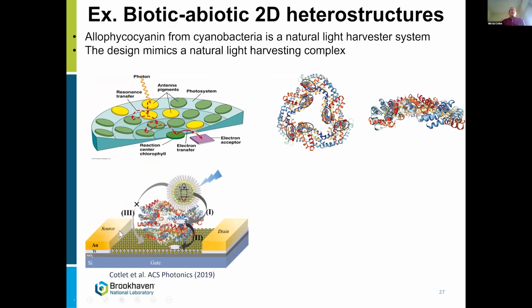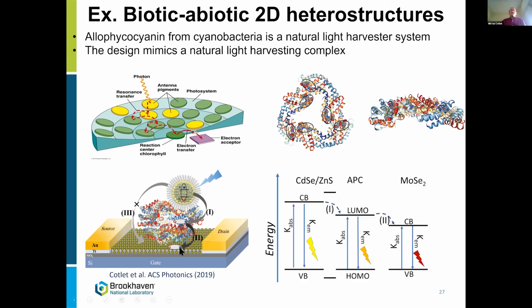We have a 2D material on which we lay down this protein, and on top of the protein, we have a quantum dot. So the idea is the quantum dot will absorb light and transfer to the protein, which has chromophores. There are chromophores in the pocket. And then the final step is going to be a transfer into the 2D material, in this particular case, molybdenum diselenide. For this to work, we have to do bandgap engineering. So we have to choose the quantum dot and the 2D material to match the optoelectronic properties of the protein. We would like to promote a directional cascade energy transfer.